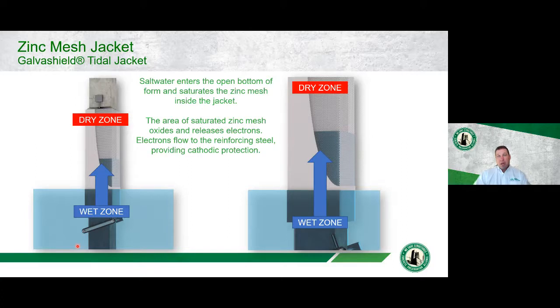Now, as you start to move up the pile, we get into our jacketed zone, and this is where we have our zinc mesh. So through the tidal fluctuation, we end up having the water wick up, or enter the bottom of the jacket system, and through the tidal action, move up and down within the limits of this jacket. And one thing to note is that within this jacket, you're going to get this water movement essentially where the tidal fluctuation is. So as you start to get up a little bit higher into the drier zone, you're going to have less and less seawater available, or less salt water available. So this area here is going to tend not to get as much current as the area down below that is immersed in the seawater at all times.